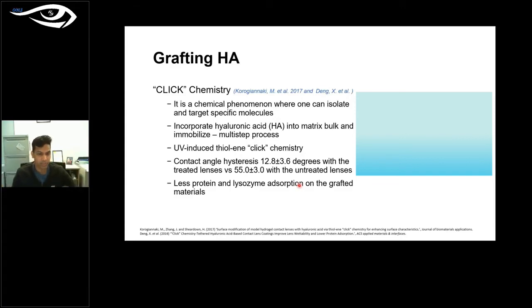That is possible with click chemistry, and using that technology, the contact angle hysteresis has been reported to be 12.8 degrees, which is fantastic. If the lens surfaces are treated using click chemistry, the angles have gone tremendously down. Whereas if the lens surfaces are not treated by click chemistry, the angles were 55 degrees. The studies have also reported that there was less protein and lysozyme adsorption on the grafted materials. Of course, which is what we want.